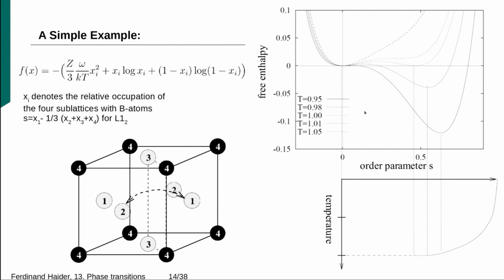This now is asymmetric, in contrast to what we saw before, because this order parameter is asymmetric. So it would matter if you exchange these sublattices here - if you put this sublattice 1 here in this sum, that's why it is asymmetric. But nevertheless, you can translate this into an order parameter.